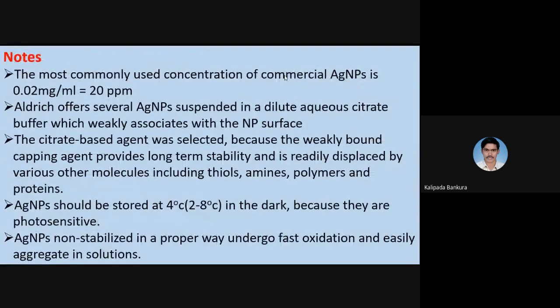Notes: the most commonly used concentration of commercial silver nanoparticles is 20 ppm. Aldrich offers several silver nanoparticles suspended in a dilute aqueous citrate buffer, which is weakly associated with the nanoparticle surface. The citrate-based agent was selected because weakly bound capping agents provide long-term stability and are readily replaced by various other molecules, including thiols, amines, polymers, and proteins. Silver nanoparticles may be stored at 4 degrees centigrade in the dark because they are photosensitive.